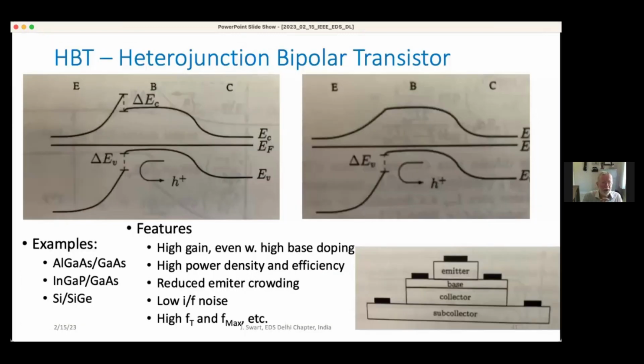For HBTs, we need to have an emitter that has larger band gap than the base in order to have high gain, even with high doping of the base. And that's possible because of the offset of the band gap. So there is some band offset in the valence band, so that it makes it less probable to emit holes from the base to the emitter. There is a little offset here in the emitter also, but you can remove this by grading the composition, the transition from the emitter, AlGaAs to gallium arsenide, removing gradually the aluminum content.